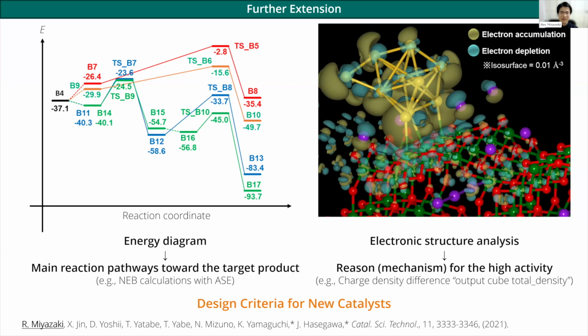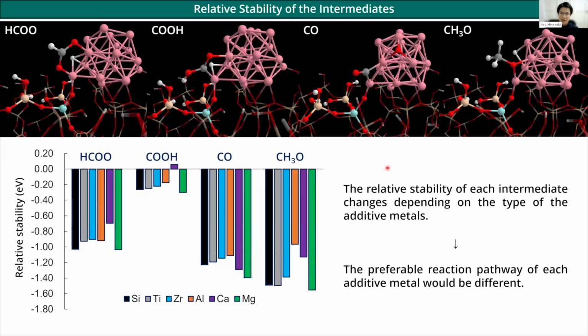Actually, that is also a very nice question. That is unknown, even now it is a very unknown part for me. My experimental collaborator mentioned that, particularly for the titanium case, they investigated the distribution of titanium at the silica support. They found that zirconium or aluminum species are randomly dispersed in the silica, meaning atomic dispersion. But for titanium, there are some atomic sites, but they also found an island structure of titanium oxide at the interface. As you know, titanium oxide probably makes some kind of cationic or charged defect of the oxygen, and that would also contribute to the high catalytic activity, I think.